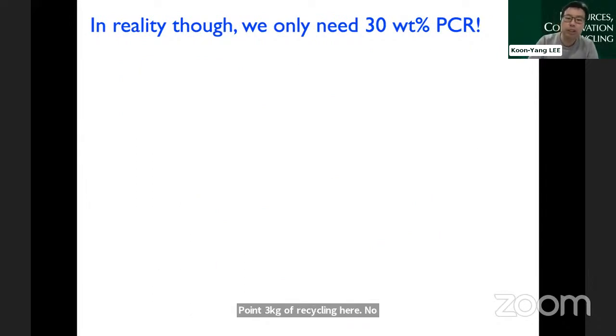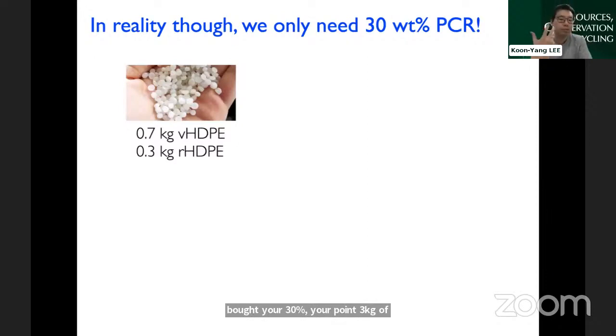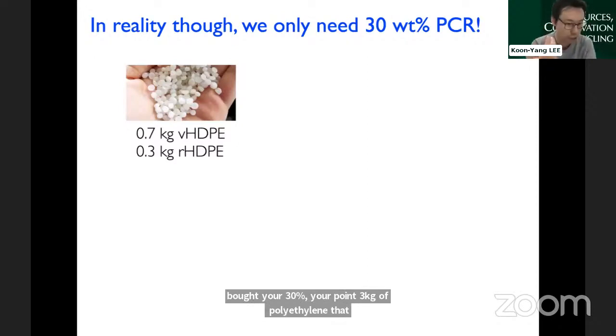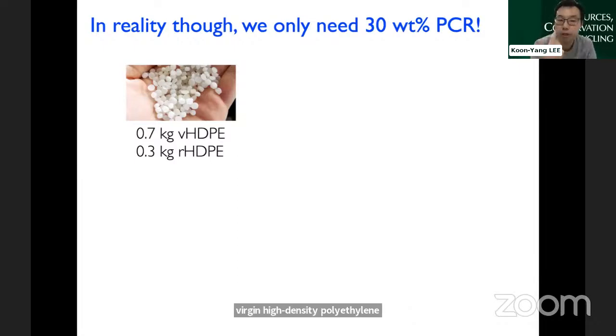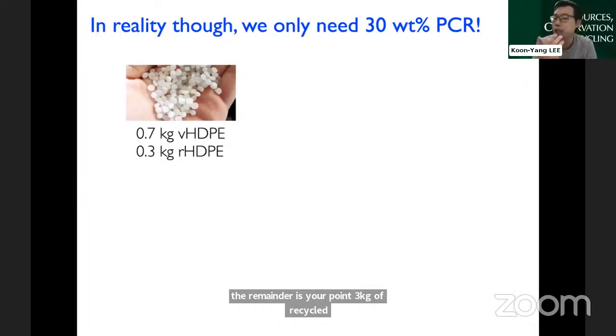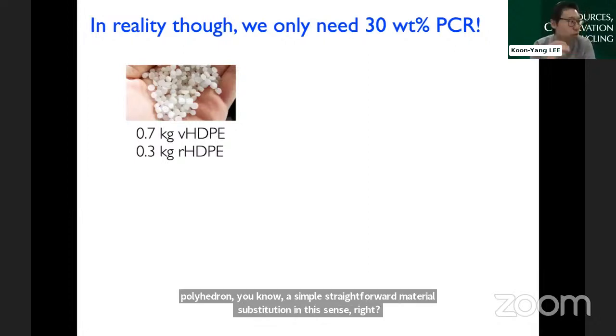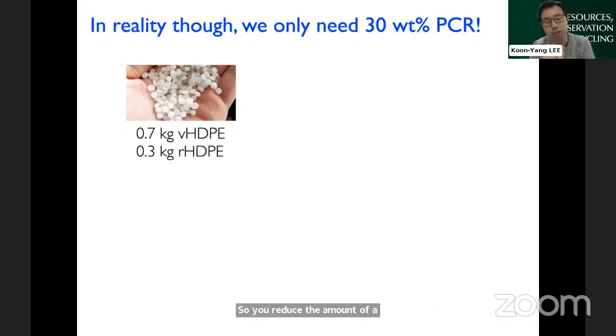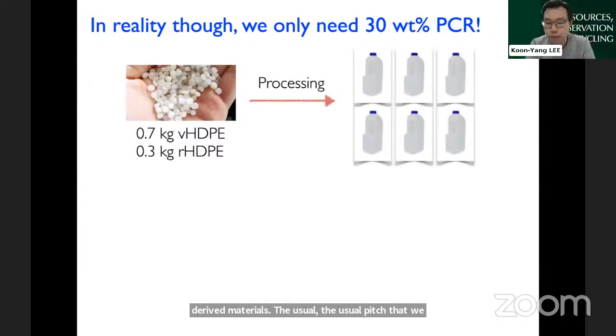Now, all right, so you bought your 30%, your 0.3 kilograms of polyethylene. That means your feedstock doesn't require 1 kilogram of virgin high-density polyethylene. All you need is 0.7 kilograms of virgin polyethylene, and the remainder is your 0.3 kilograms of recycled polyethylene. A simple, straightforward material substitution, right? So you reduce the amount of virgin fossil-derived materials, the usual pitch that we make when it comes to sustainability. Mix them together, and process them into, again, 1 kilogram worth of milk bottles.